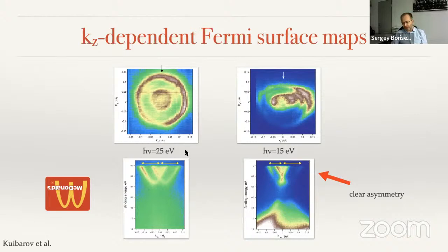Now coming back to the very famous Fermi surface, which has been measured many, many times by different groups, we call the underlying dispersion a McDonald's. In this case, it's clear why. This is the Fermi surface taken at 25 eV, conventional energies, and we see basically what other people see. Perhaps one could see an additional set of features here, which says that there are more features than just these 2 parabolas. But the data set at 15 eV was surprising to us, because this is a conventional analyzer, but the direction shown by this arrow is the vertical direction. And it shows that there is a symmetry. And this symmetry is not expected if these states are just surface states. It's a pretty clear symmetry, right? Again, the intensity distribution here is a bit strange. There are no distortions because this is along the slit. So this is not an artifact.